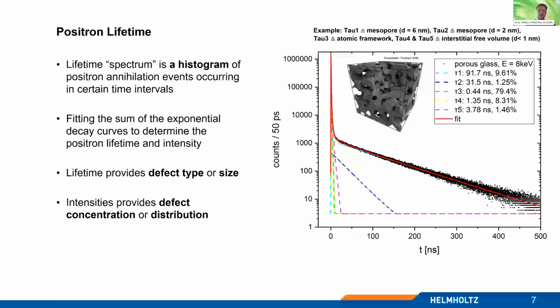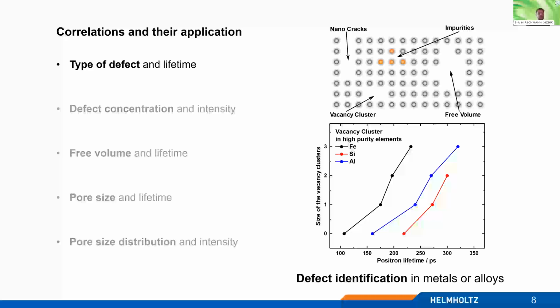And as you see, you can get the lifetime itself, which is correlated to the defect type or the size, and you can get the intensity, and this is correlated to the concentration or the variation within the material. So each of these parameters, so lifetime itself and the appropriate intensity, can be correlated to certain properties of the material. Here, for example, we measured vacancy clusters in high purity elements. And as you see, for each element you have, for the defect-free material, a defined lifetime, which is, for example, for iron, 108 to 110 picoseconds.